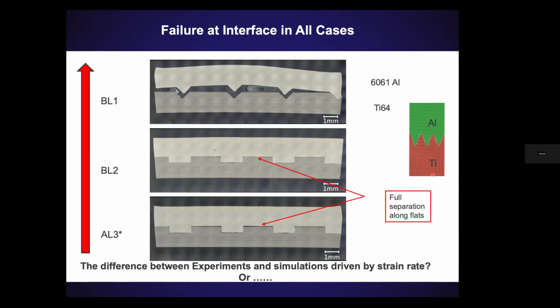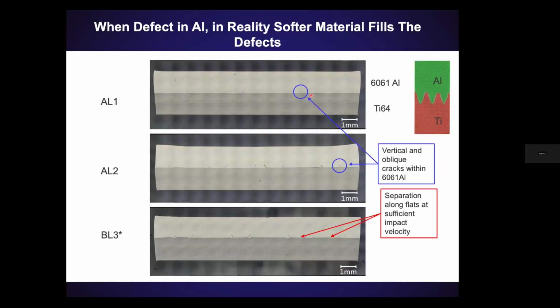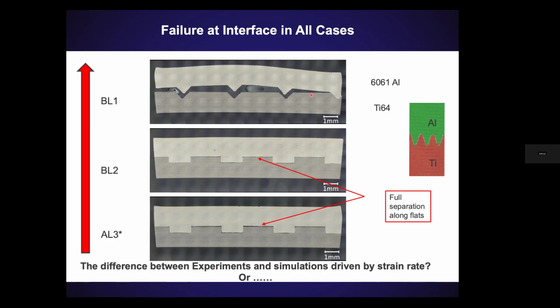The other thing is, the length scale of this cell is about 30 angstrom. This sample here, this is my 1 millimeter scale bar, right? So what I'm looking at in MD is this very small region if I had to zoom in. There could be strain rate issues. There could be a lot of things going on. But I think one thing that we did figure out from looking at molecular dynamics and experiments was that, in general, if you add these rough interfaces in the material, while they might reduce your initial yield strength, they might, depending on their shape, improve your long-term ductility or delay the failure in the material. At least that's what we're seeing experimentally.